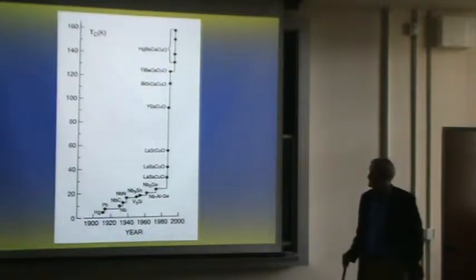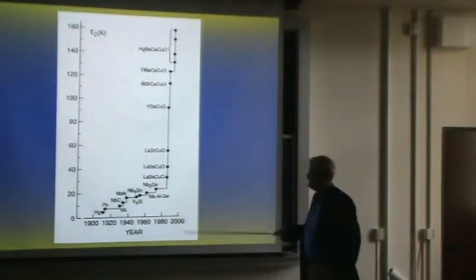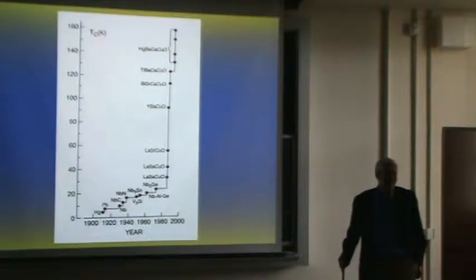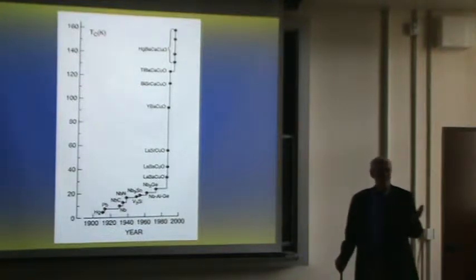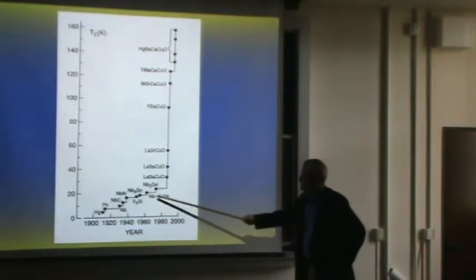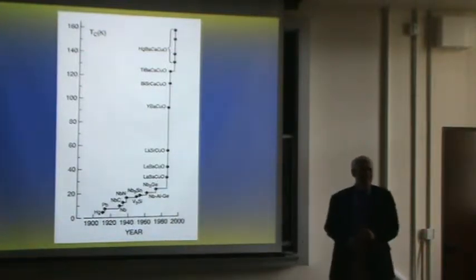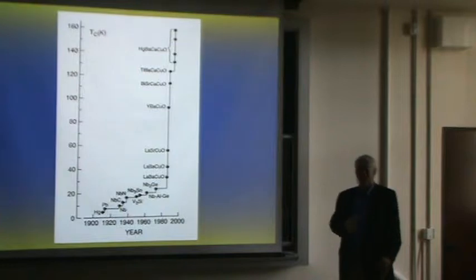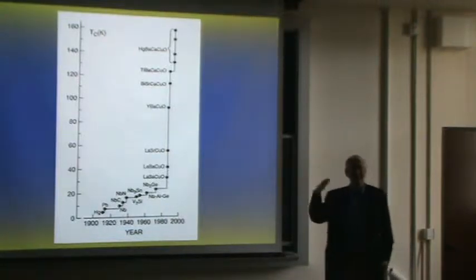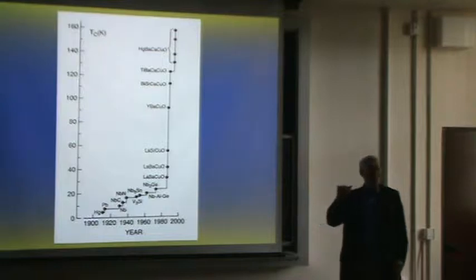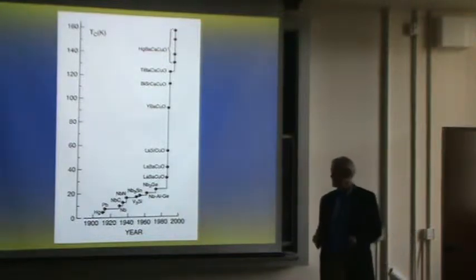I actually had my first personal introduction to superconductivity in the material vanadium three silicon. A couple of colleagues and I, in one of my first projects as an independent scientist, looked at the phonons in the material because of phonon-mediated superconductivity. And these materials, all of them which have high temperatures, have the oddity that the structure distorts just before they become a superconductor. Many people felt that the structure distorting and the quite high superconducting temperatures must be connected in some way.